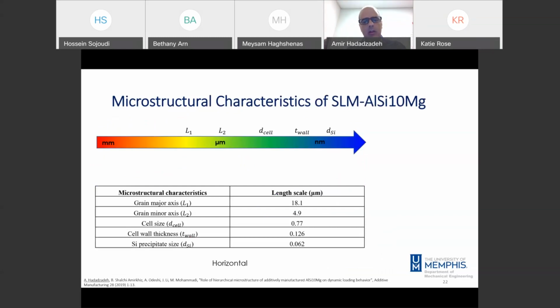So far, in the AlSi10Mg material, I was able to show the hierarchy in the structure. Again, we have silicon precipitates, with a size of 62 nanometers. We have cell wall thickness, again, with this size, 0.126 micron. We have cell size or cell structure and grain structure with different sizes. And again, as you see here, the features in the microstructure of AlSi10Mg are spanning almost 3 orders of magnitude or 3 length scales, from nanometer scale up to sub-millimeter scale over here.